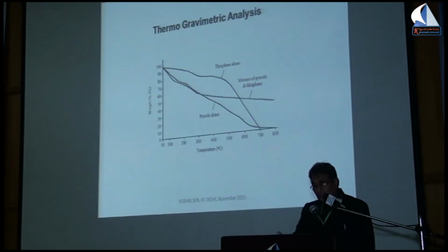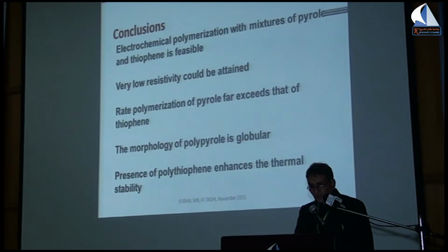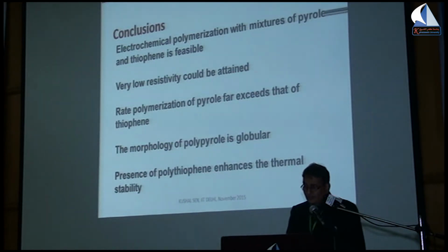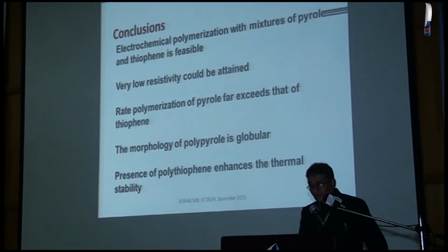But these tests were done, for example, on some films, and these films still stay up to 500, 600 degrees centigrade. You can actually see them. It shows that thiophene is a stronger one, it's more stable. Polypyrrole is less stable, but together they help each other and they become slightly better, with stability in between.